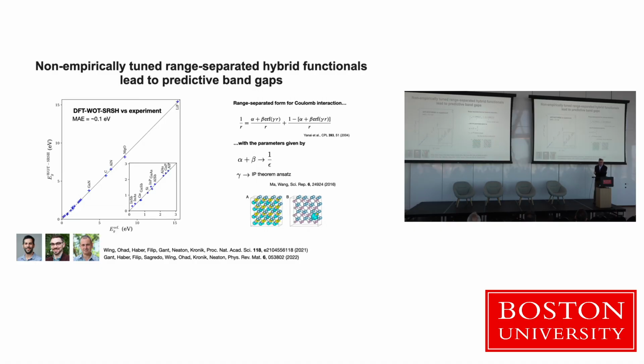And so the way the functional works, I'm not going to get into it very much, but essentially what you do is you evaluate the exchange operator exactly, and so you rewrite 1 over r with the identity shown up here that introduces 3 parameters. And then you tune those 3 parameters to satisfy boundary conditions and theorems of DFT as best you can. And we have a way of doing that, and that was a little bit of a challenge, particularly for some of the theorems involving electron removal for solids.